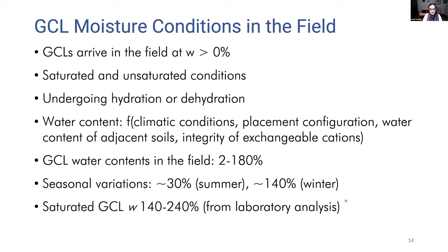If we look at GCL moisture conditions in the field, we see that first of all, these materials arrive in the field at water contents above zero. These are highly active materials. The clay mineral is very active and it tends to absorb moisture from the atmosphere. The GCL is produced in a dry factory environment and transported under dry conditions. However, simply because of being exposed to air, at some point along the line, the material tends to absorb moisture and again arrives on site at high moisture content.